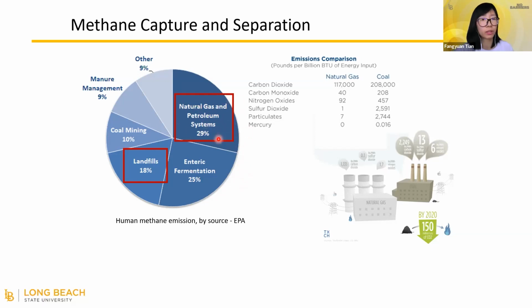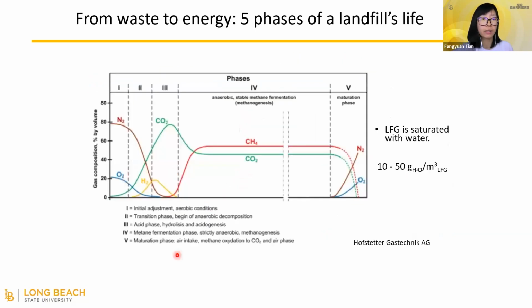So it's much simpler to purify the methane from those oil rigs, because it's just pure methane coming out, compared to the landfills. The landfills have a mixture of methane and carbon dioxide, especially at phase 4 when the landfill is mature, about 50% methane and almost 50% carbon dioxide, mixed together with some impurity gases, including oxygen, nitrogen, and lots of water. So it's much more difficult to extract methane from a mixture of different gases. But if we could use that methane, we can convert waste to energy, and you basically need nothing from the landfill, so it's free, and we can generate much more economic benefits.